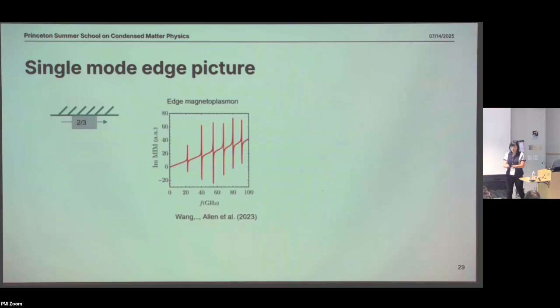Then what this microwave signal carries at the edge would be two parts. One part is the edge magnetoplasmon. There have been theories taking care of this, showing that inside this 0 to 100 gigahertz regime, with the parameters that we have, it has many resonances. The resonance frequencies are different for different edge states. It depends on the charge, and it's proportional to the effective charge squared.